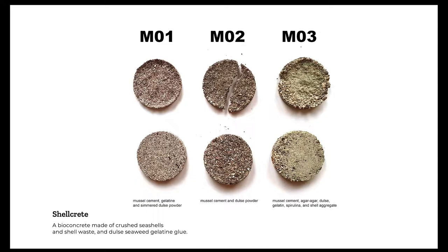The next application I developed was a shellcrete. Historically, especially in coastal cities around Florida and the Faroe Islands, shells were heated up to 800 degrees Celsius to create quicklime because there was no limestone in the area to create cement. I didn't have access to a kiln but I did have my oven, so I heated mussel shells from waste — from eating mussels — to about 200 degrees Celsius for about half an hour to an hour, then crushed them.